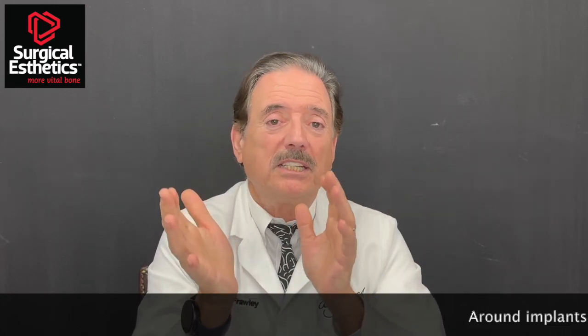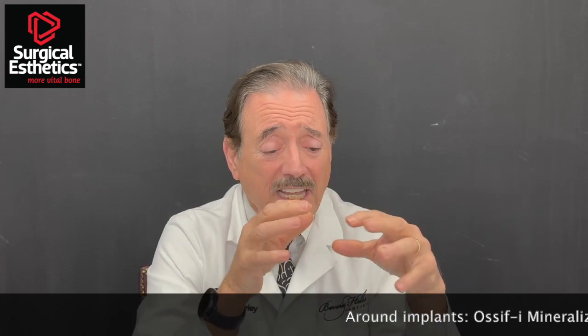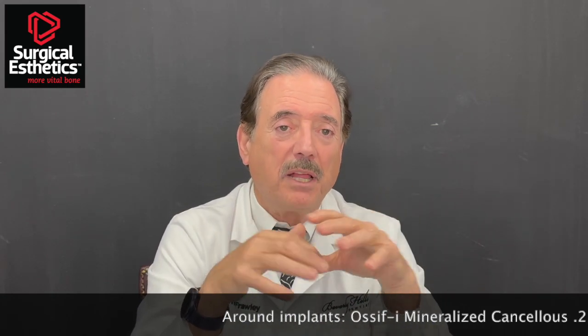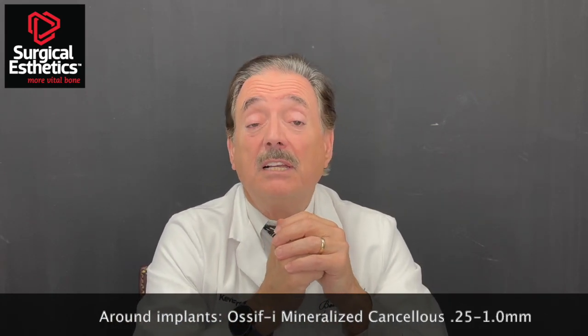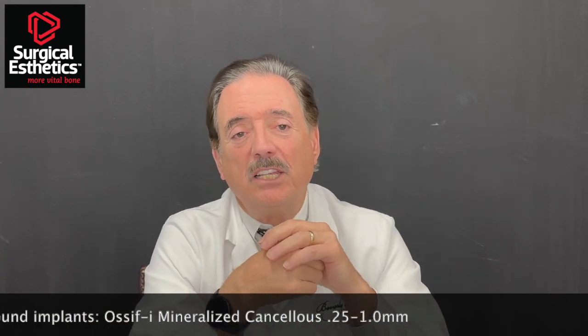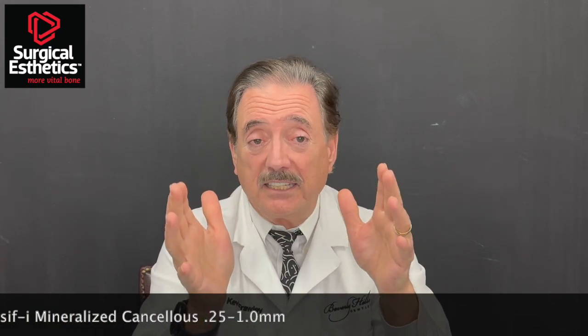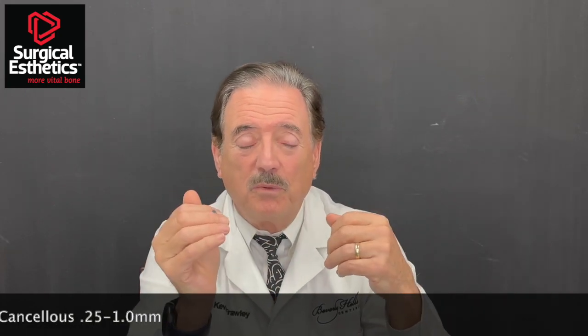Around implants, if you're placing an implant and you've got some defects around that implant that you're packing, again, you want to use a mineralized material, and the smaller particle mineralized cancellous, which is a .25 to 1.0mm, is a good choice there.